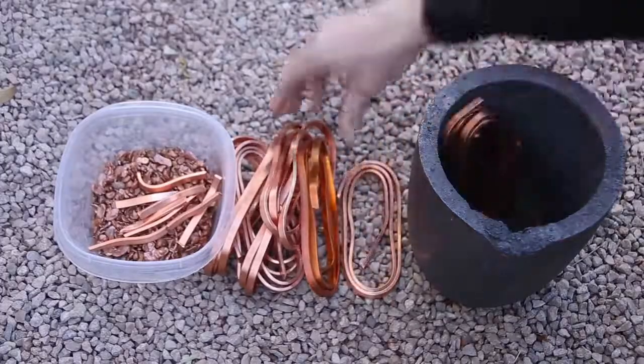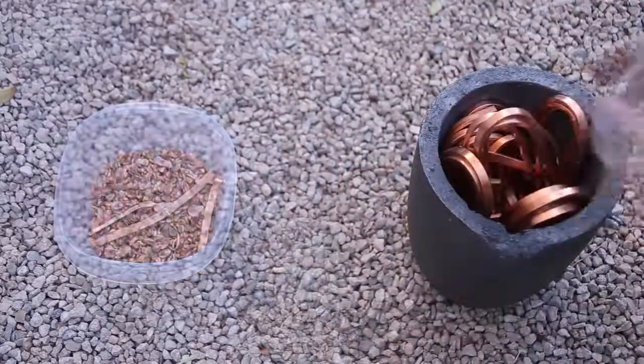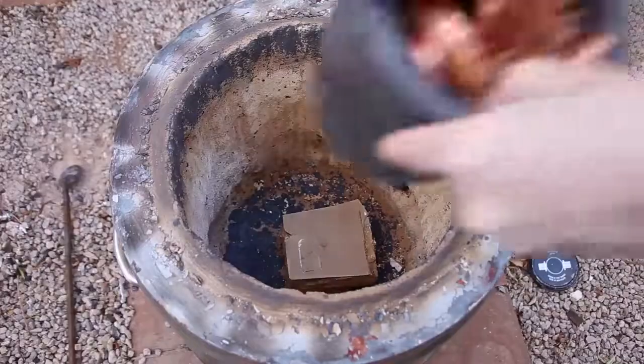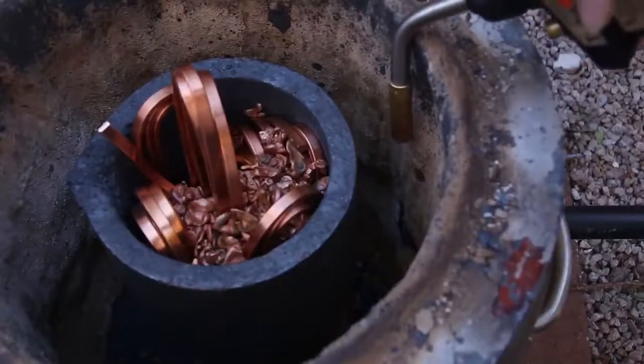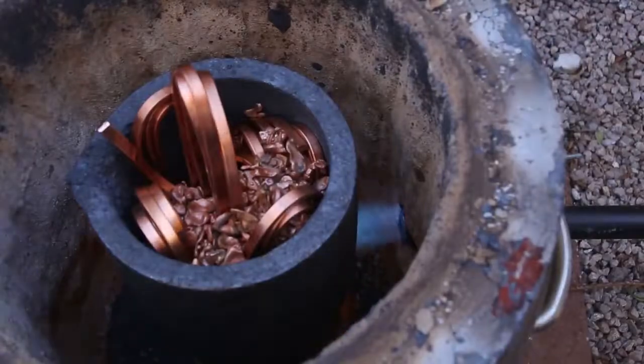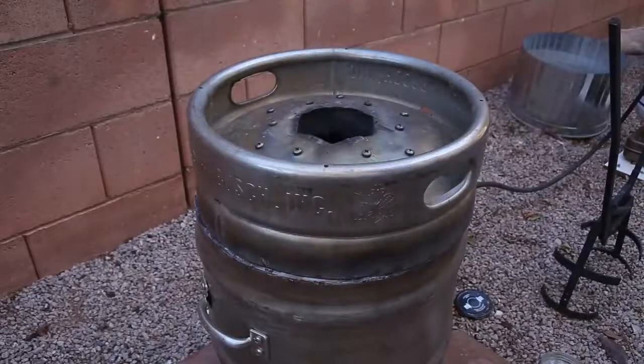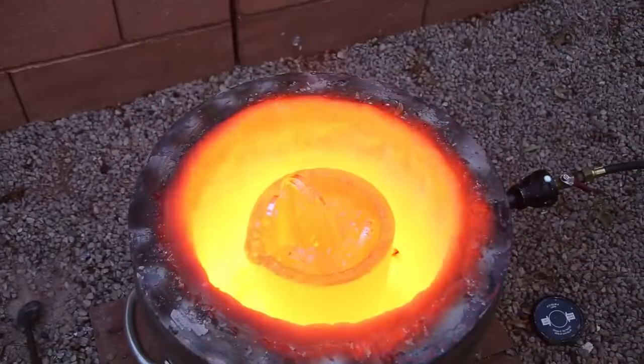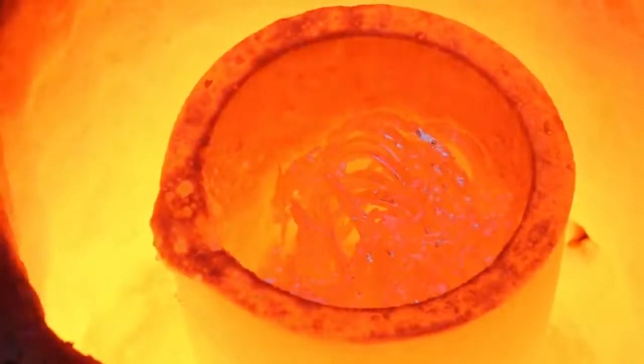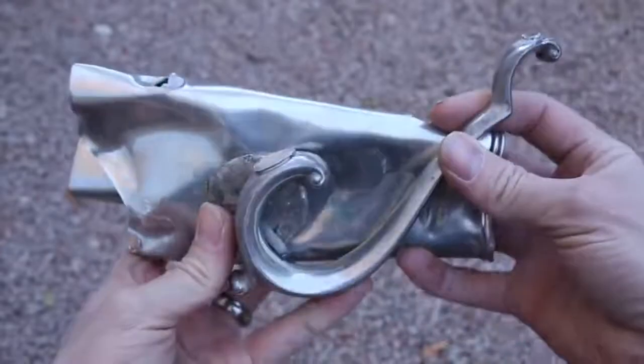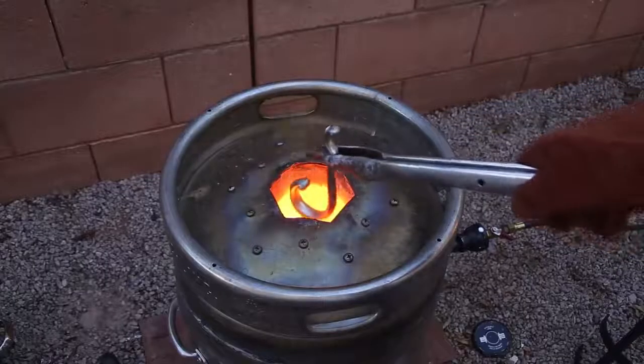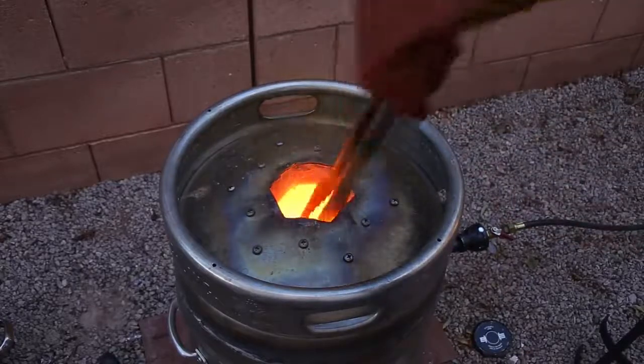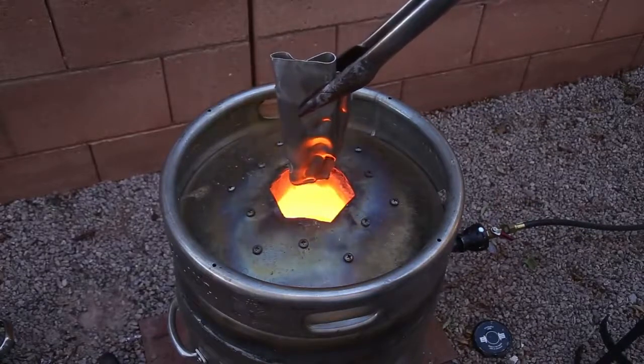Now that the shell was done, it was time to melt some metal. For this casting, I needed to make some bronze consisting of 90% copper and 10% tin. First, I melted 9 pounds of copper, which took about 30 minutes in my homemade furnace. Once the copper was melted, I added the tin, which instantly melted in the molten copper. This is because tin has a melting point of 450 degrees Fahrenheit, or 230 degrees Celsius, while copper has a melting point of 1984 degrees Fahrenheit, or 1085 degrees Celsius.